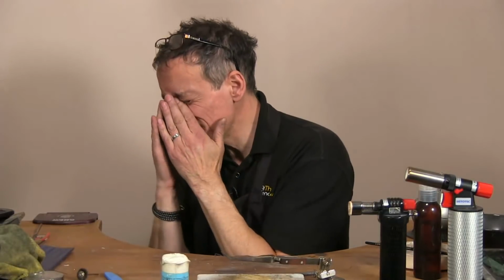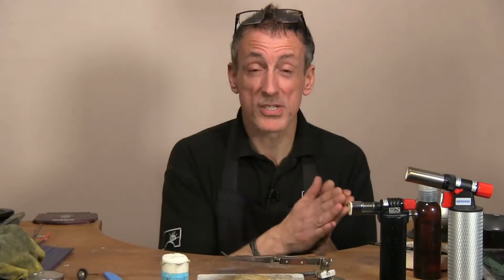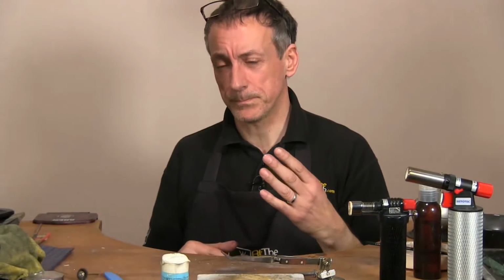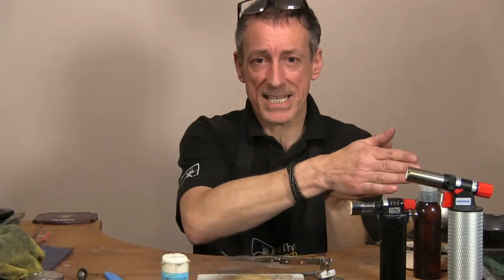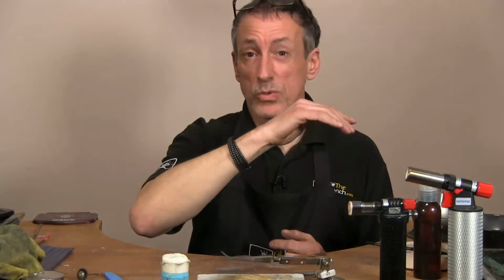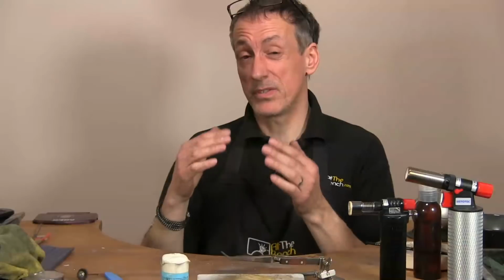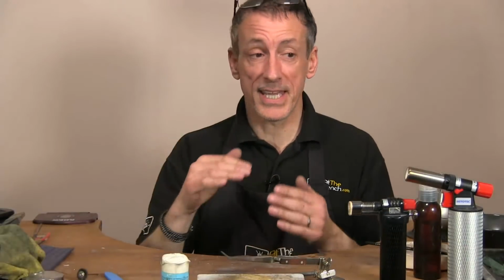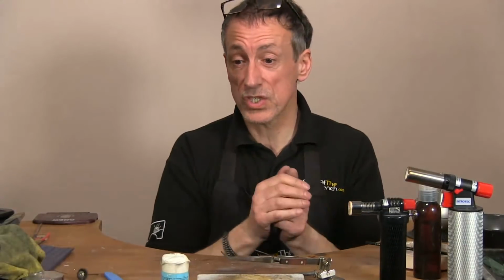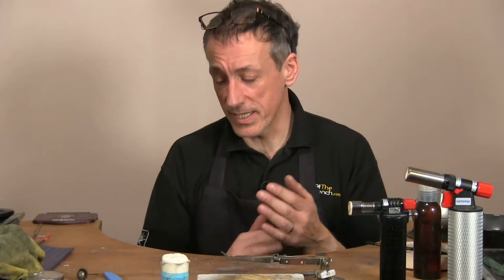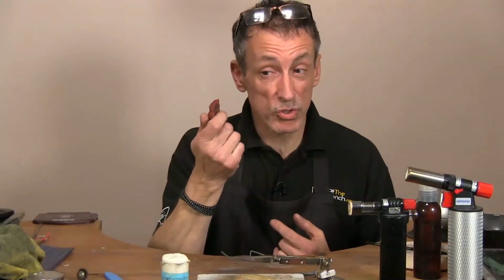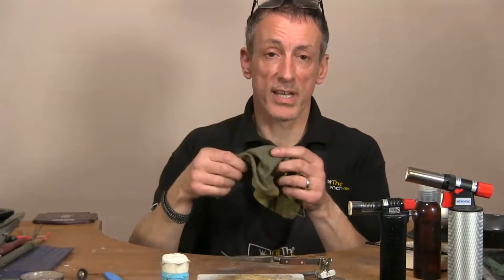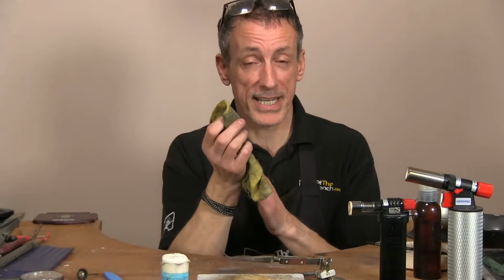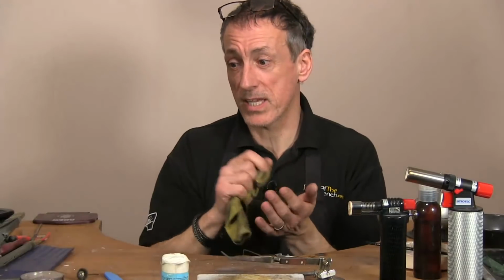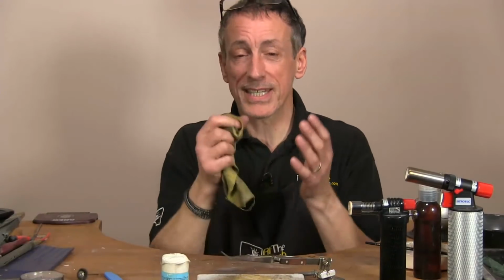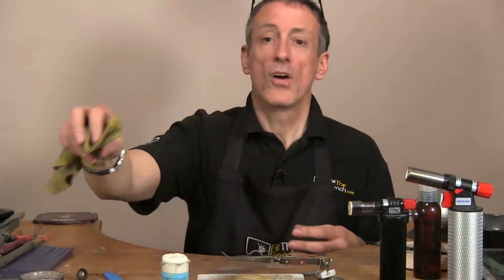And what was the third part? Maintaining the polish. You can't. If you do highly polish it and you solder and you put it in the acid, the acid will strip out that very, very thin layer, especially if you're using silver. It'll strip out that thin layer, and then you're left with a gorgeous white finish. Then you can just repolish it gently with a bit of rouge, or even just go over it with a nice soft cloth, perhaps impregnated with rouge, just to bring that polish back. But that would be the only way. You're never going to keep that polish on the piece all the time.